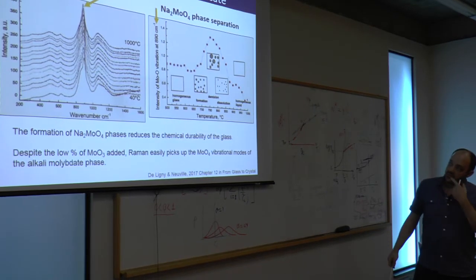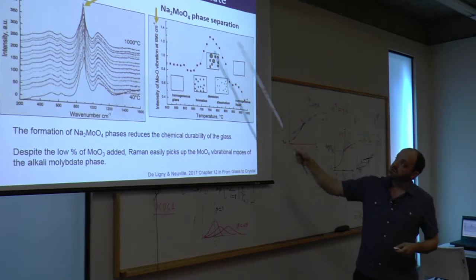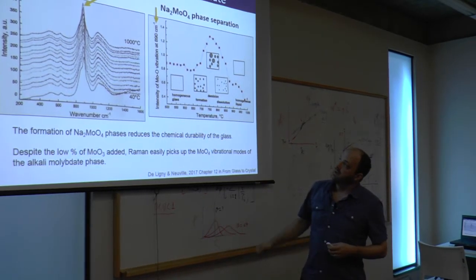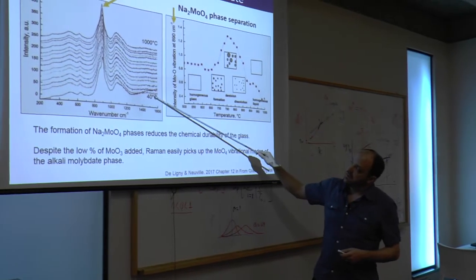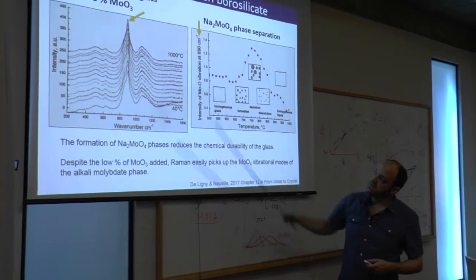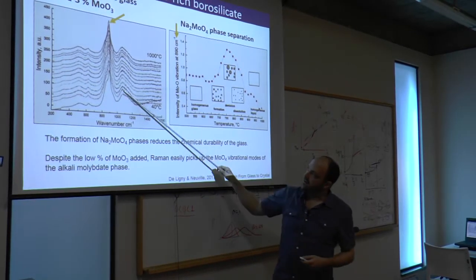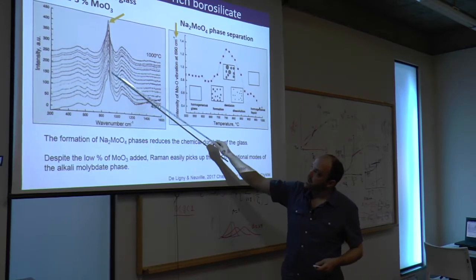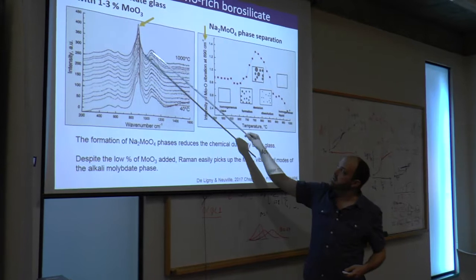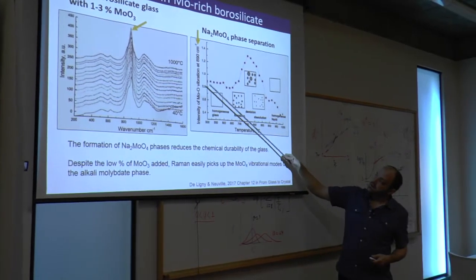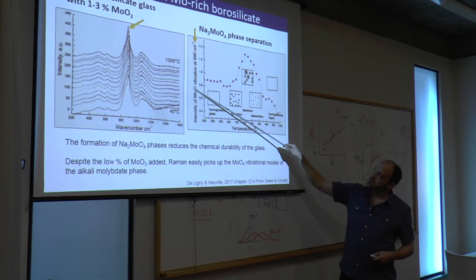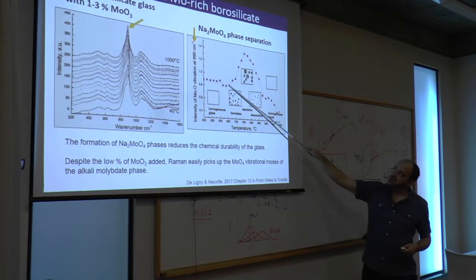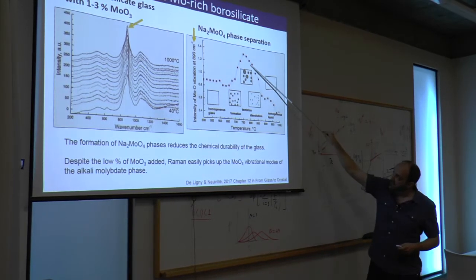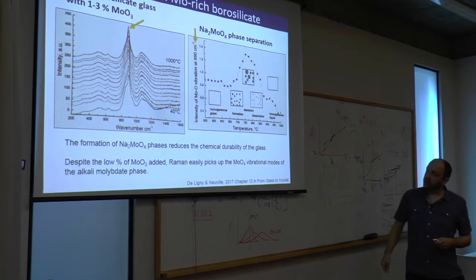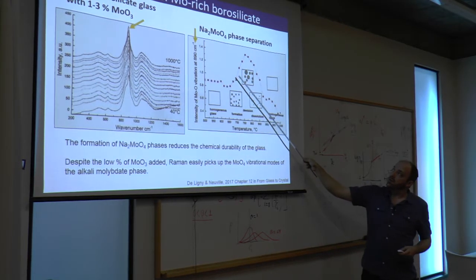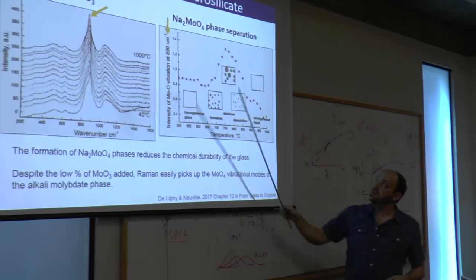This is a nice example of high temperature work. It's in a borosilicate glass where they've added molybdenum. And this is, instead of composition now, temperature going from around room temperature to 1,000 degrees. And you can see that everything sort of overlaps. This is perhaps not the best display of these spectra. But this band, if you plot the intensity with temperature, you can see that their assignment is related to molybdenum oxygen vibrations. And you see almost no change in the intensity, quite a rapid increase before a decrease at higher temperature. And their interpretation is that it increases when you have the phase separation of this sodium molybdate.